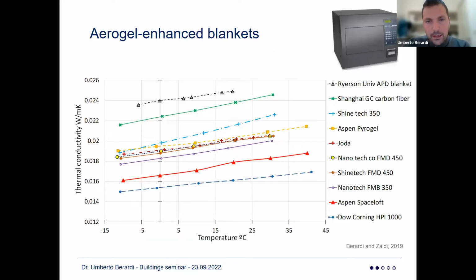Now, just to give you the sense of where we are right now, our product is not necessarily as effective as a few others, but the price is 5 times smaller. Our products tend to be in the range of thermal conductivity of 0.02. When you do ambient pressure drying, you don't really get rid of all the liquid portion, so you get a bit of a higher thermal conductivity. On the other side, the products that use supercritical, high pressure conditions need an autoclave, and they are hard to make for the market and to fight for becoming the dominant insulating material in the building industry, because producing this kind of material tends to be more expensive and only in small sample sizes.